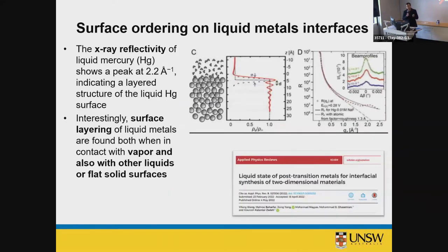Now, I mentioned about surface layering. So if you do X-ray reflectivity measurements for mercury, for gallium, for tin in melting in a liquid state, you see that you can see a peak, and this peak associates with the order on the surface. For mercury, you see that 2.2 angstrom. The surface layering is happening anytime you have an interface. It can be interface with vacuum, interface with vapor, interface with other liquids or solids. Okay, what does it mean? Surface become very, very ordered.